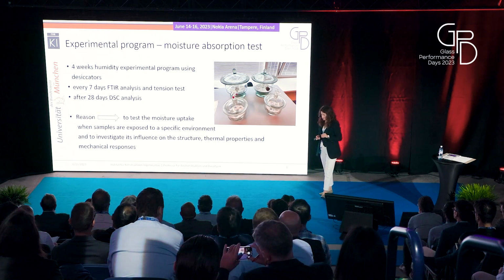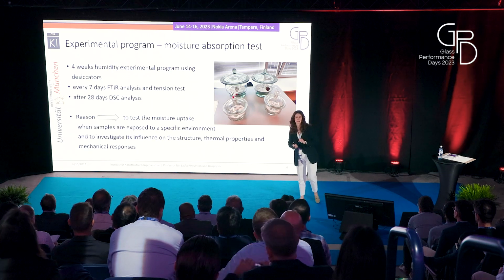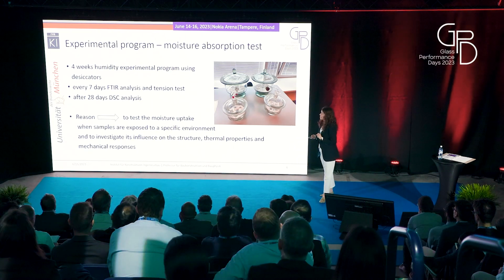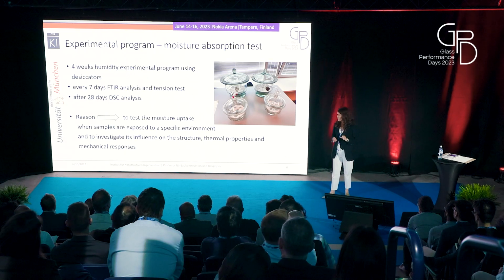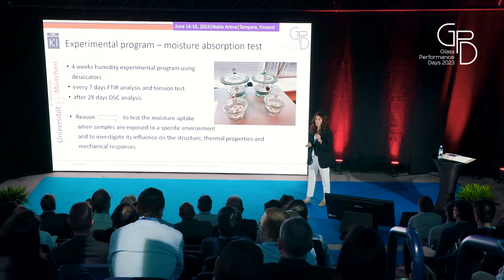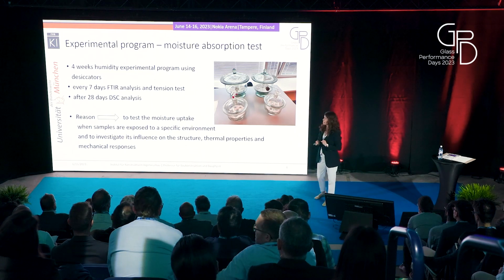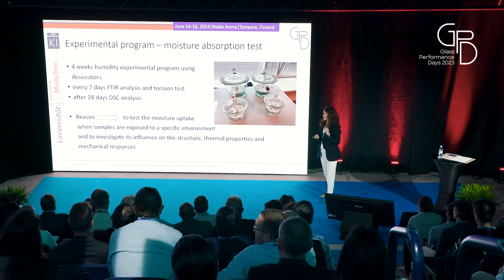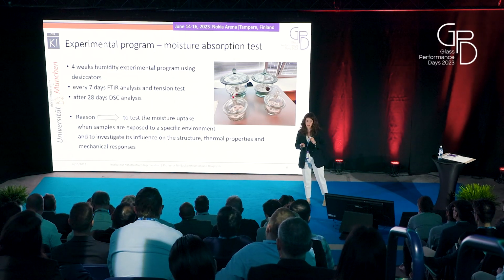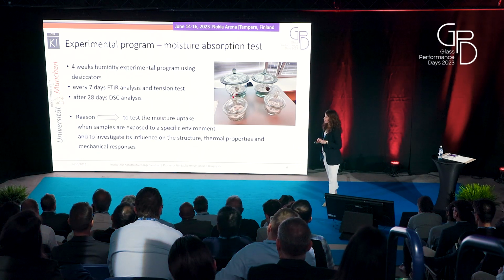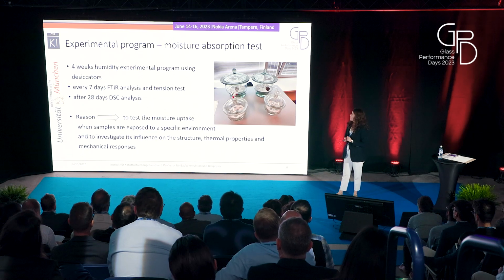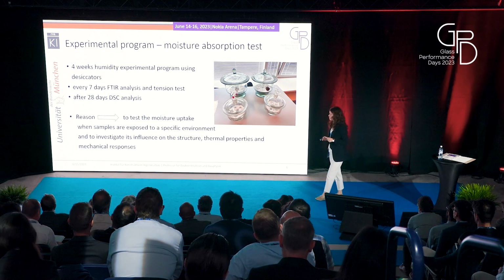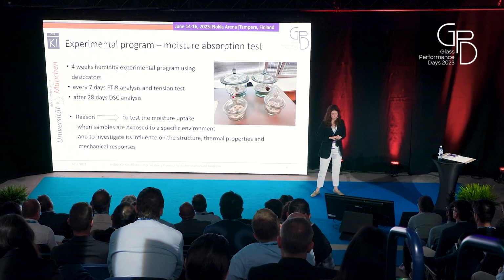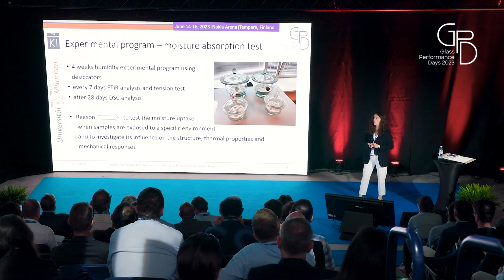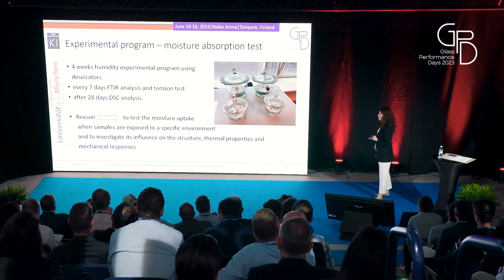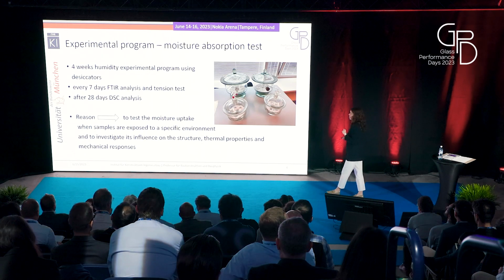In addition to that, before we exposed our specimens to this experimental program, we did the tension tests on both of the interlayers before they were exposed to the humidity program. We also did the infrared spectroscopy for it, and we also did the differential scanning calorimetry. So we had results for both of these interlayers before they were exposed. The reason for this was to test the moisture uptake when samples were exposed to a specific environment, and to investigate the influence on the structure, the thermal properties and the mechanical response.